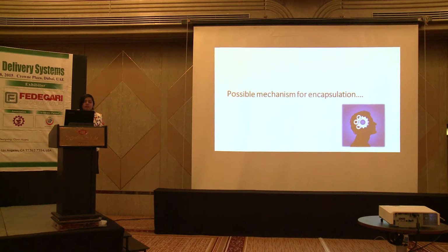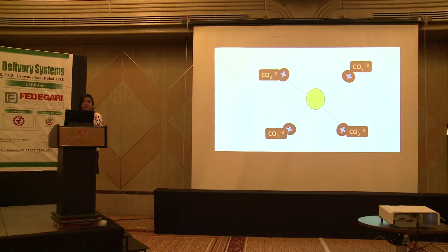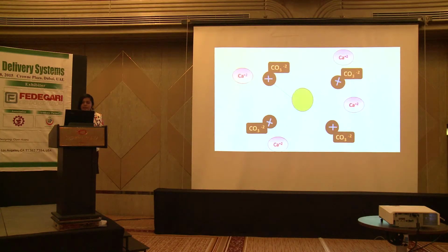So, let's see what the mechanism of encapsulation is. The surfactant has a hydrophobic tail and a hydrophilic head. The hydrophobic tail bonds to the drug. To the hydrophilic head, which has a positive charge, the carbonate anion of the sodium carbonate solution bonds. Then, to that carbonate anion, the calcium ions of the calcium chloride solution bind. Therefore, it forms calcium carbonate.